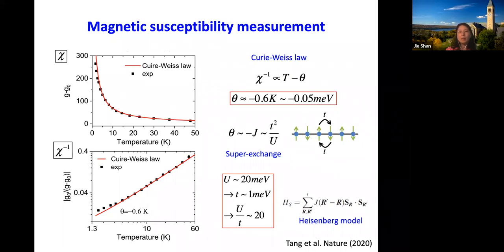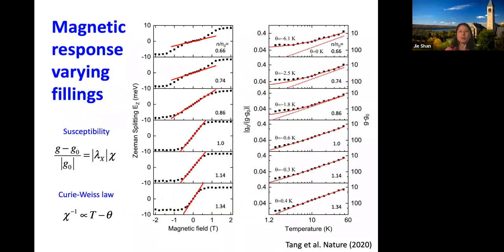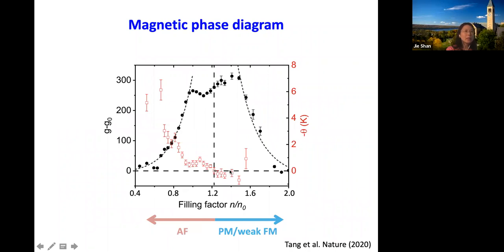And then the next thing, of course, we did is to sweep away from half filling and look at how the Curie-Weiss temperature changes. So let me go to that data. So this is the magnetic phase diagram we obtained using this technique as a function of filling. The black dots are the g factors. You can think of them as magnetic susceptibility, and it can be very large. Those dashed lines are just guides to the eye. It looks like it tries to diverge at those 2 points.